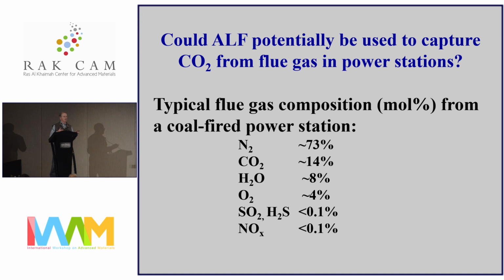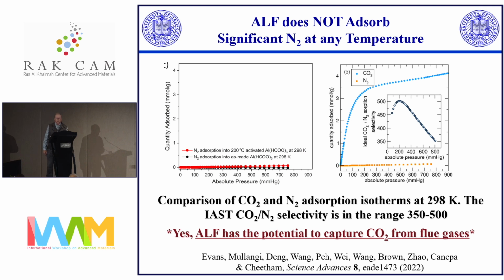So since we can capture CO2, could it potentially be used to capture CO2 from flue gases in power stations? And so the first separation that we looked at with this was to see, will it adsorb nitrogen? Because most of the flue gas is nitrogen, and people, of course, want to capture the CO2 from things like coal-fired power plants. So we looked at nitrogen adsorption, and much to our surprise, it does not adsorb any nitrogen at all. Even though, as Mohammed's just shown you, the difference in size between CO2 and nitrogen is like 0.2 of an angstrom, the kinetic diameter.